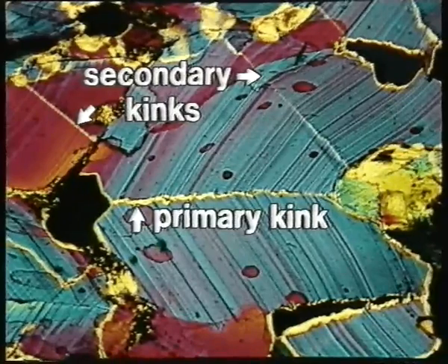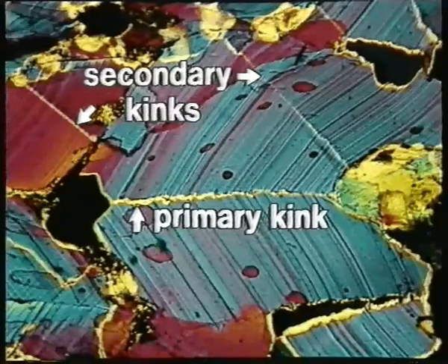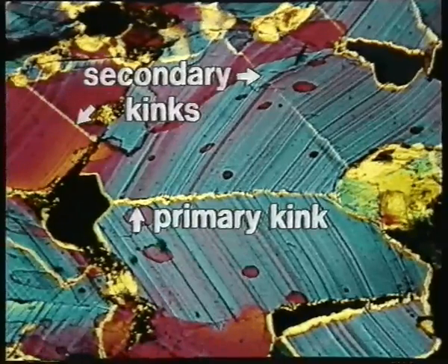These irregularities are due to the bulging and migration of the boundaries. Grain nucleation and growth, as seen in the grains marked with the crosses, also preferentially occurs in the kink band. These new grains are initially strain-free and are probably nucleated as part of a strain softening process. This allows the kink band to accommodate continued shortening.